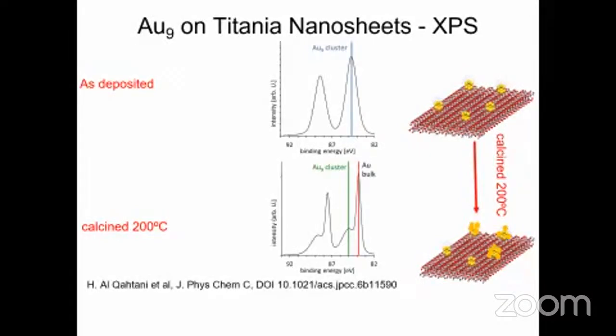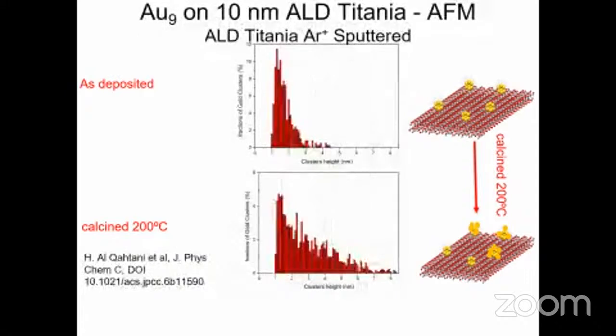We also use atomic layer deposition, which is a very thin titanium deposit on the substrate with a thickness of 10 nanometer. We study this kind of nanocluster aggregation and the degree of aggregation on different titanium oxides. Like we tried the nano sheet and we tried P25, and now we tried the atomic layer deposition.